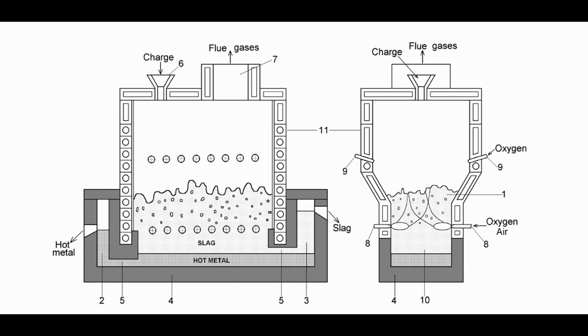There is about 70 tons of metal and 100 tons of slag in the furnace. Two lined chambers, sumps, are situated each at one of the end sides of the furnace. They are used for separating tapped metal and slag. The sumps are connected with the working space by channels of different heights. This ensures separate transportation of metal and slag into the metal and slag sumps. There are holes for tapping metal and slag, which are located at different heights. That ensures continuous free tapping of the melting products at a speed that matches the unit capacity. If the furnace has little capacity, tapping may be arranged periodically.